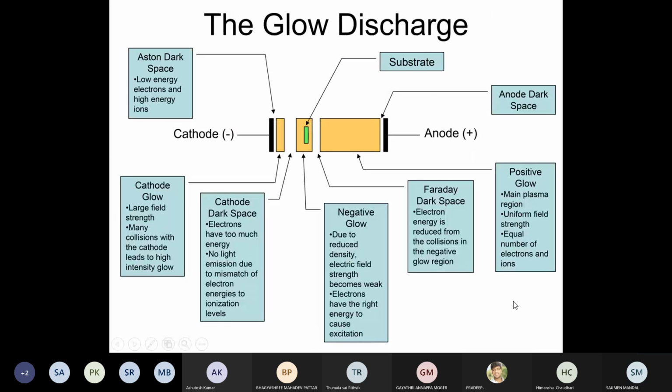That's why in sputtering, chamber pressure is extremely important. If you change the pressure, people measure the quality of the film, and it's highly dependent on the chamber pressure. Another is the cathode-anode distance, which you don't have the liberty to change. If you purchase one instrument, there will be a fixed distance between the cathode and anode.